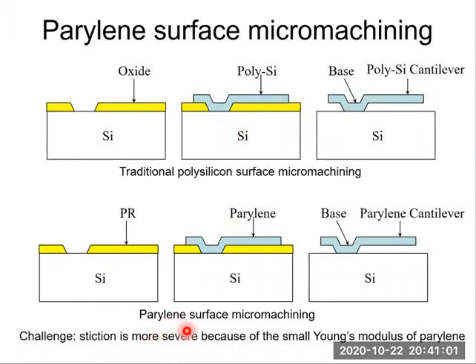But parylene surface micromachining has a challenge. What is the challenge? Stiction is more severe because of the small Young's modulus of parylene. Parylene is much softer than polysilicon. So stiction can occur much more easily for a parylene cantilever. That's the challenge we have to overcome for parylene surface micromachining.